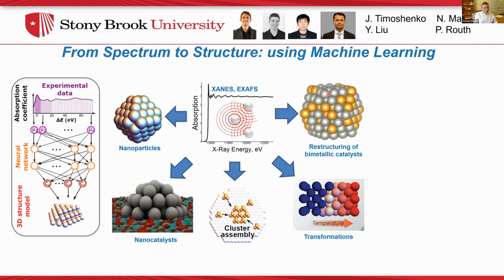more traditional method. But in using X-ray absorption fine structure, we're limited to very well-defined data, very high-quality data that usually can be obtained only in very friendly conditions, concentrated samples, low temperature, and very uniform samples. And so when you do experiments in operando conditions, you usually have something just the opposite. You have high temperature, low loading, and harsh reaction conditions in general, including reactor walls and some limitations in geometry. And so we don't get that luxury of getting good quality EXAFS spectra to obtain coordination numbers and distances and other important parameters. And so we resorted to look into XANES as an alternative, and it was very rewarding.